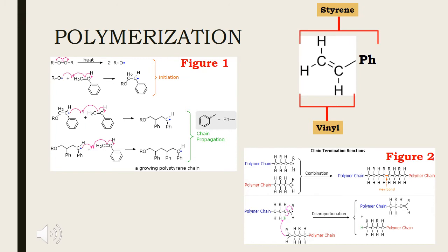Theoretically, this radical polymerization may propagate unchecked, producing few extremely long polymer chains. But in actuality, a large number of moderate-sized chains are formed, indicating that chain-terminating reactions are taking place. The most common termination processes are radical combination and disproportionation.